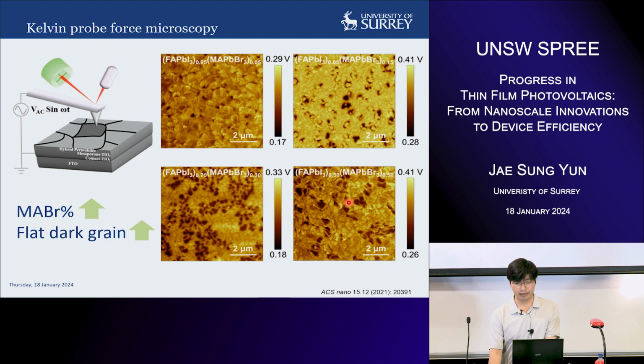So, and that sort of saturates at 30%, and we see a stronger, very large contrast between the grains, which means that there is a huge difference between work functions. So there is clearly a very inhomogeneous distribution of your grains from the beginning.